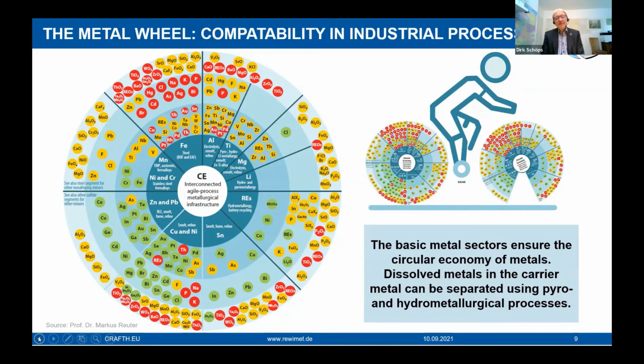Yeah. We have some cases where metals even can be recovered from the slag of the melting process. For instance, when you look at the tin process, then you can see that tantalum oxide has a red dot. This means that tantalum cannot be obtained from the tin smelter, but the contents of tantalum in tin slags are sometimes very high, up to 1.5 or 2% tantalum in the tin slag, so that the tin slag itself can be used as an input material for the tantalum recovery.